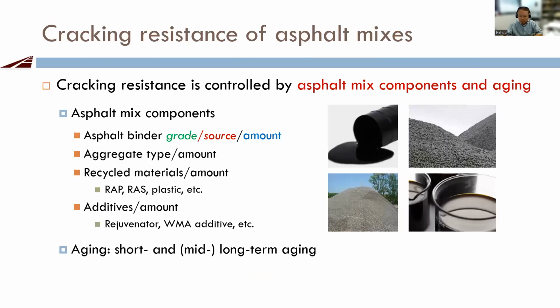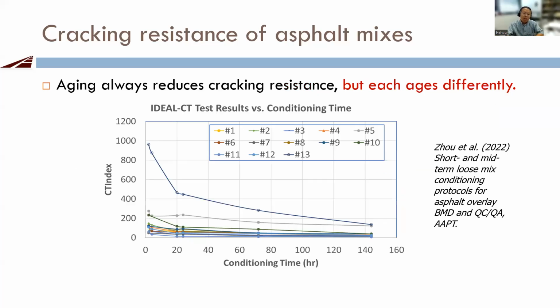So let's talk about what the issues are with our most common mixes right now. It is cracking. We all know we have cracking issues. This cracking is controlled by many mix components and aging. I would say that in order to get better cracking resistance, you have to work on all these areas. But I want to say again, as I mentioned, aging is a significant factor for cracking resistance. And specifically here, I have 13 mixes on this IDEAL-CT test result. All these mixes have the same gradation.